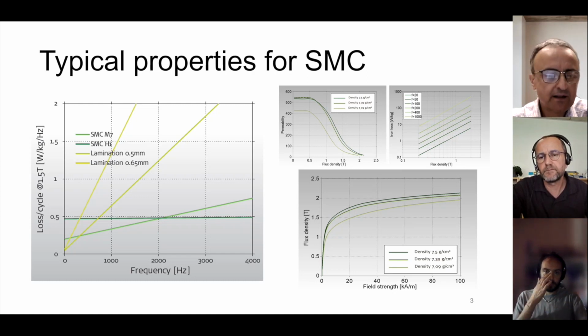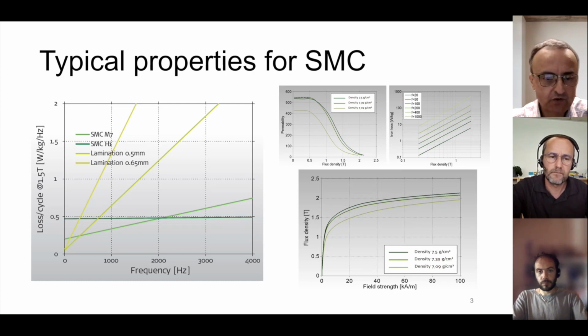And when you go for a different material, the M7, then you can see lower hysteresis losses, which are the ones that you can see at the beginning of the scale, which sum up with increasing eddy current losses. And there is exactly the effect of the process you described. So you have a somewhat less effective insulation between the particles, so you have increasing eddy current losses, but you get better annealing, which means lower hysteresis losses. So it's a matter of a trade-off.